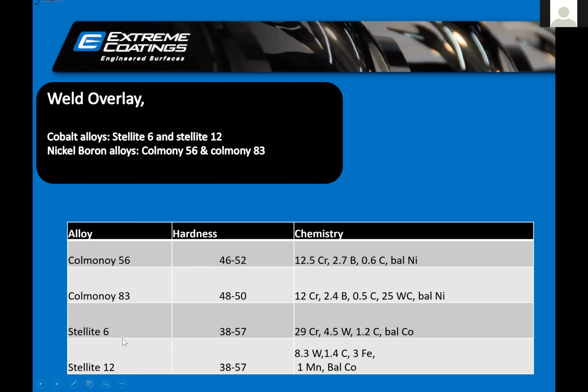So you may often hear from Indian screw suppliers that we also do bimetallic. Technically, they are correct. They do welding of Stellite 6, but the tungsten percentage in that is only 4.5%. Then there are some Chinese, Taiwanese companies that give a little bit more compared to Stellite 6, known as Stellite 12. The tungsten percentage is almost 8.3% there. This is better than Stellite 6.